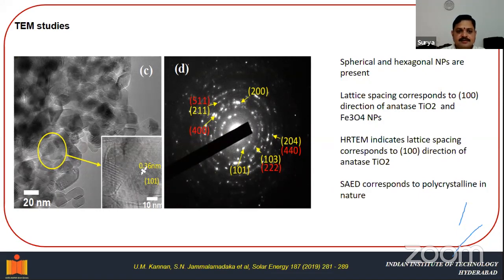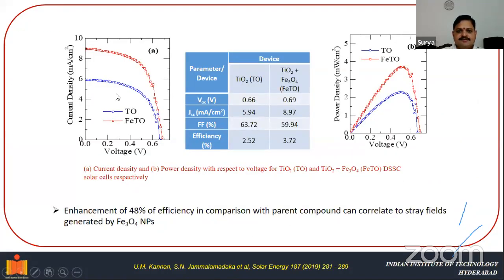In the sense that the nanoparticles have spherical and hexagonal shapes, and from the lattice spacing we could find the gap between two lattices. It is around 0.36 nanometers, and the diffraction ring confirms that our film is polycrystalline in nature. Okay, this is the kind of JV characteristics that we have obtained.